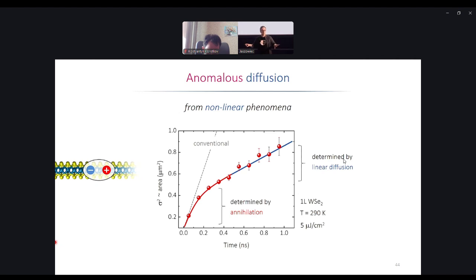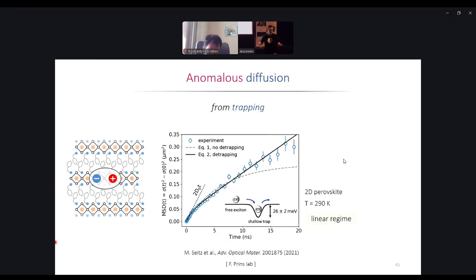So if the excitons repel each other. And then again, think about material which is not perfect. Real material has, what does it have? Defects, traps, right? So what can happen, and this is an example for perovskites, is that the opposite is the case. In the beginning you have free diffusion. So in the first nanosecond, this is where the free diffusion takes place, and then increasingly the exciton distribution becomes localized, and then you have the super sub-diffusive behavior in the time dependence.